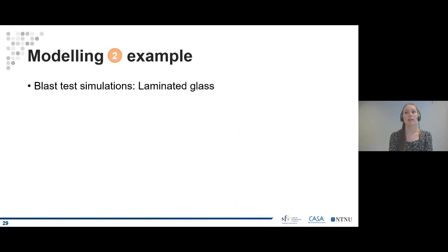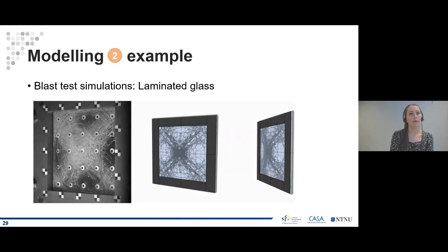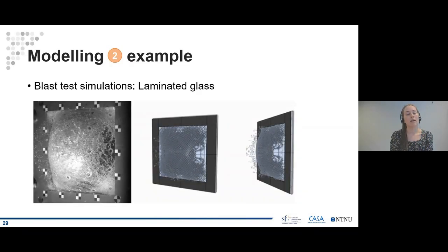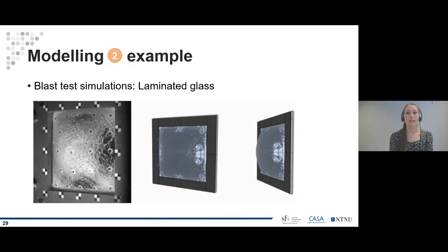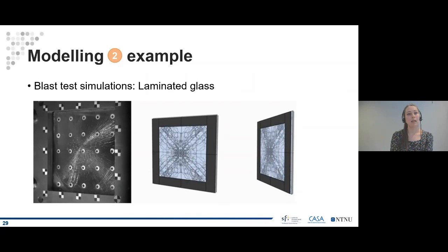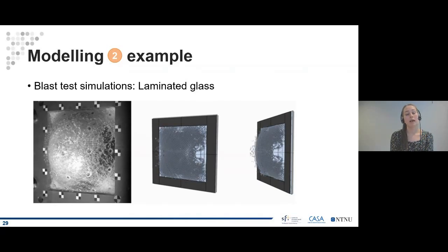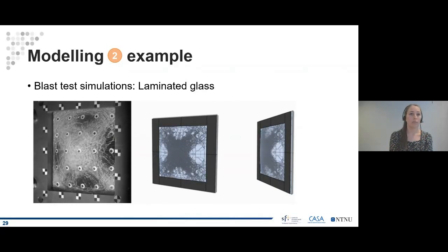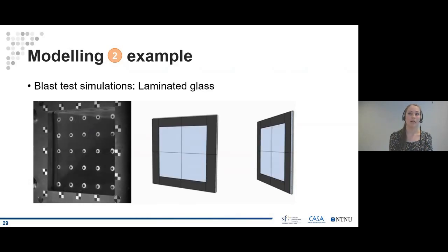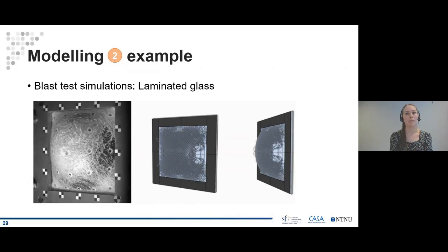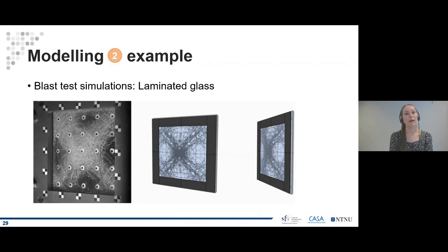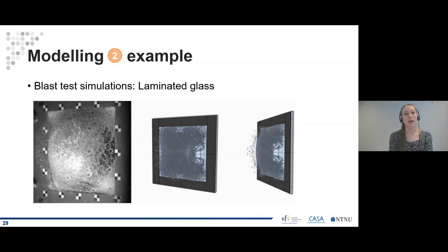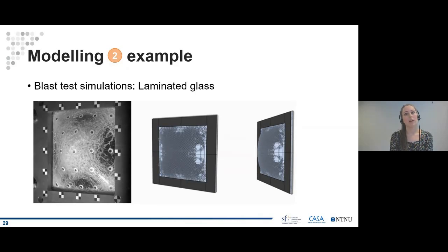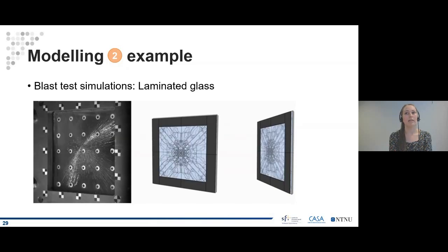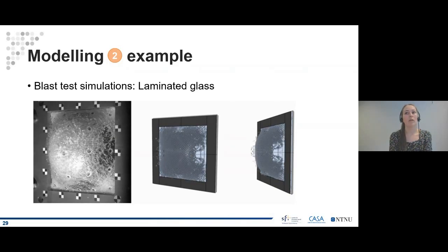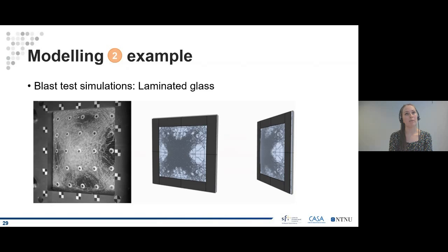Now for the laminated glass test, and here you can see the comparison. Again, we see that the mechanisms are the same in the test and the simulation. We get quite a similar fracture pattern with diagonal cracks towards the boundaries and very fine cracking of the glass. And we are also able to describe this detachment or delamination of some of these small glass fragments from the PVB.